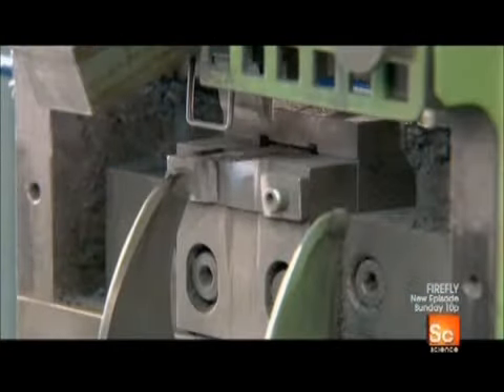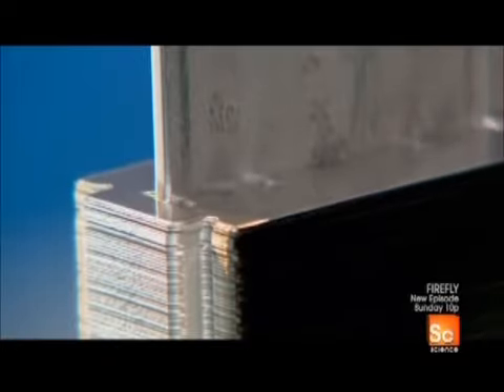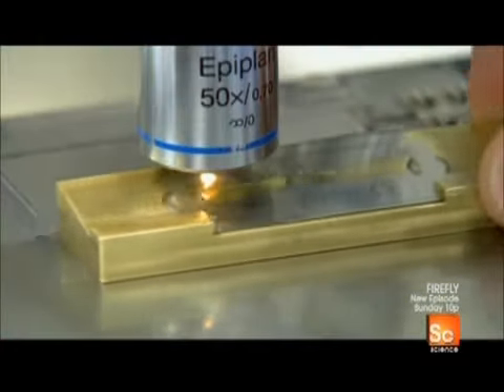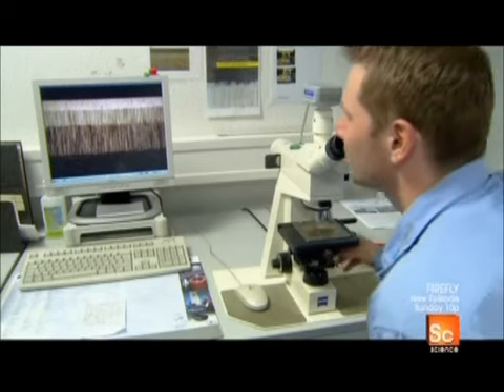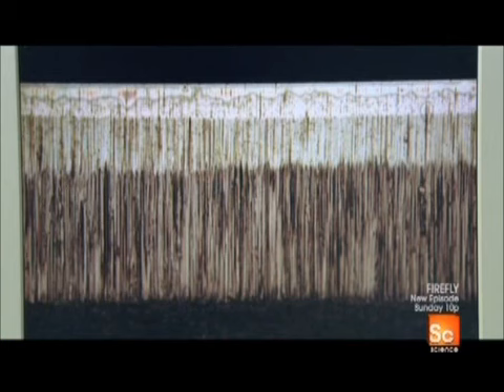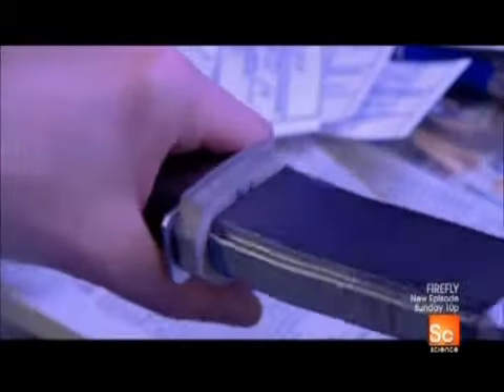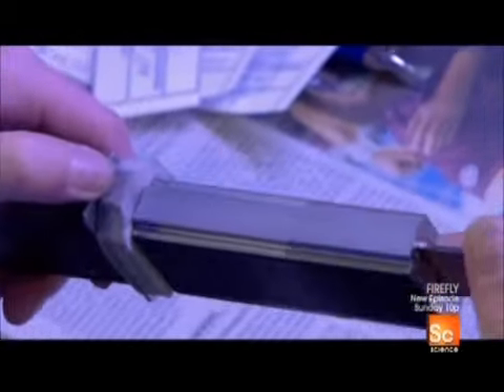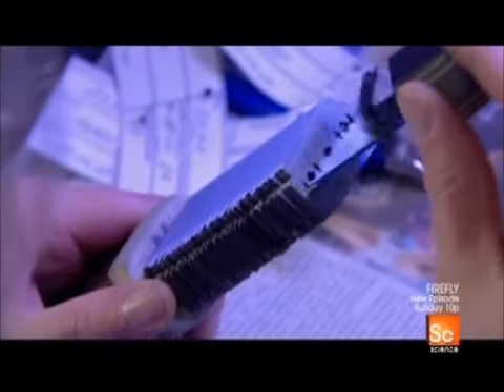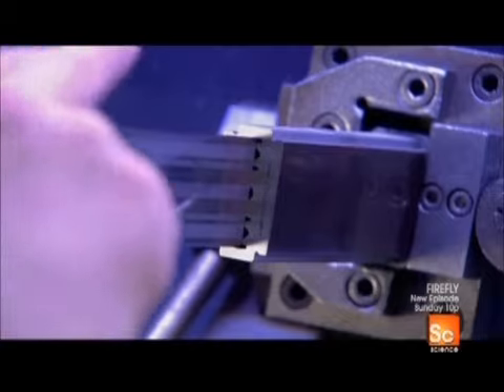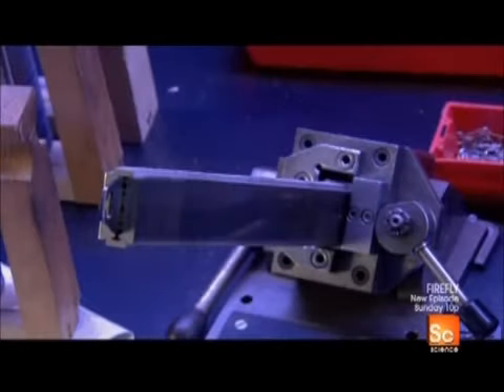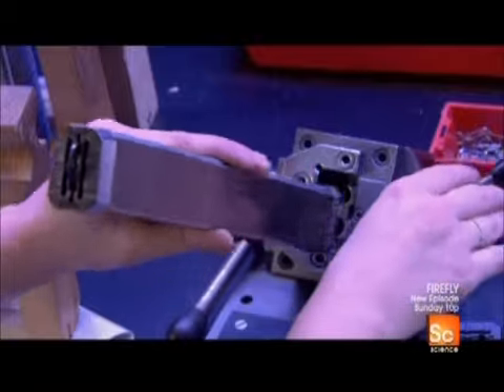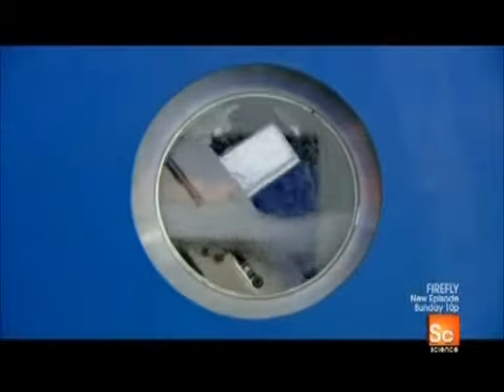Until now, the blades have been connected to each other. As they exit this machine, a knife separates them. The factory's quality control lab pulls samples from the production line and checks, among other criteria, the quality of the grinding and geometrics of the cutting edges. Then, every single blade the factory produces is examined for cutting-edge defects. Technicians assemble blades in packs of up to 800, then shine fluorescent light on the 2 cutting-edge sides. This makes defects visible. Blades that pass this inspection are washed with solvent to remove contaminants.